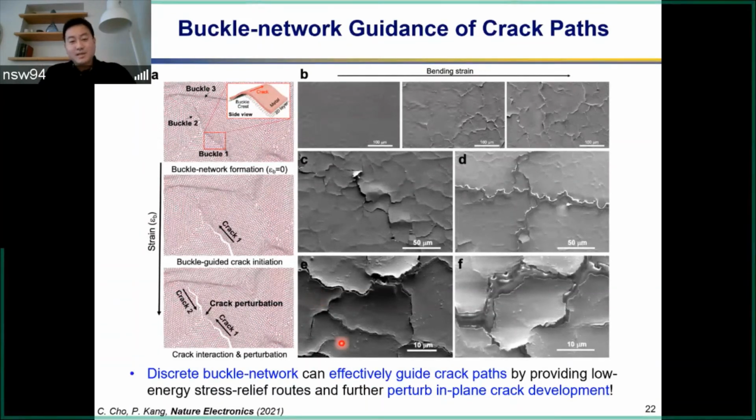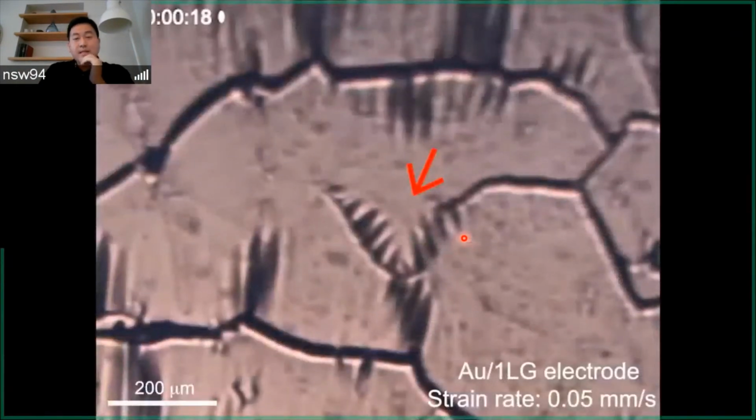That also is partly responsible for connecting the current, because it's not straight, it's not lengthening the gap, whereas with an irregular shape, you have another irregular shape, you have a chance of also touching. So it's like a somewhat percolated type of electrical conductance model, but really that buckle initiated fracture connected with this irregular feature is what uniquely allowed this electrical feature.